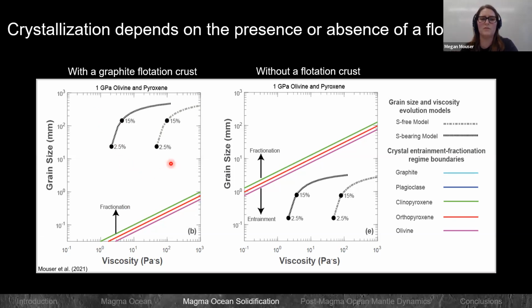So starting with the graphite flotation crust, you can see that the solidification timescale is long enough that you can create grain sizes, or potential grain sizes, that would be large enough that they would fractionate from the system. So we would expect fractional crystallization to occur with this scenario. If you go to a scenario without a flotation crust, because you have such a short solidification timescale, the grain sizes will be so small that they will remain entrained within the liquid. So in this case, we would expect something more along the lines of batch crystallization.